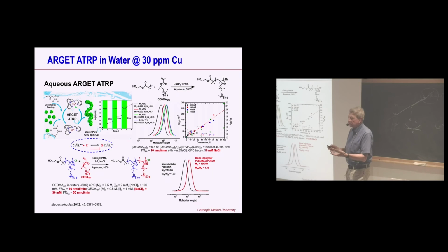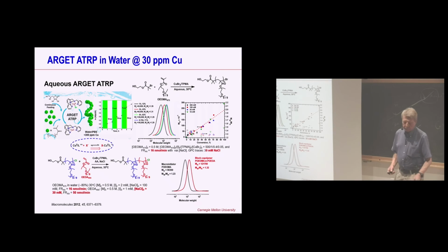So this is highly dissociated, and you don't have a deactivator to control polymerization. By using Le Chatelier's principle, you can add a little bit of salt, sodium chloride or sodium bromide, and now you have enough deactivators. We use sodium chloride at 30 millimolar, and polymerization is very well controlled, with good control of molar masses. You can make block copolymers and control the reaction properly.